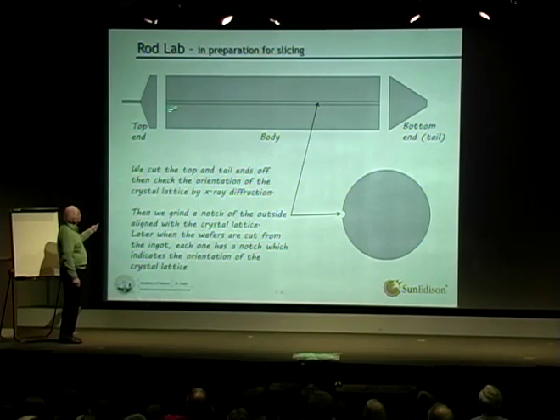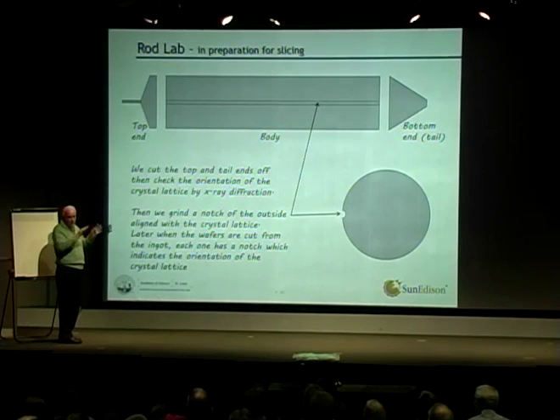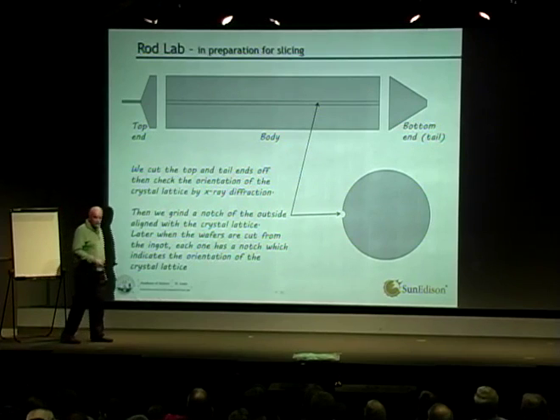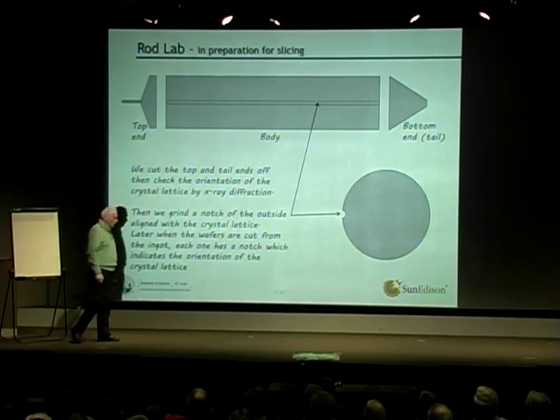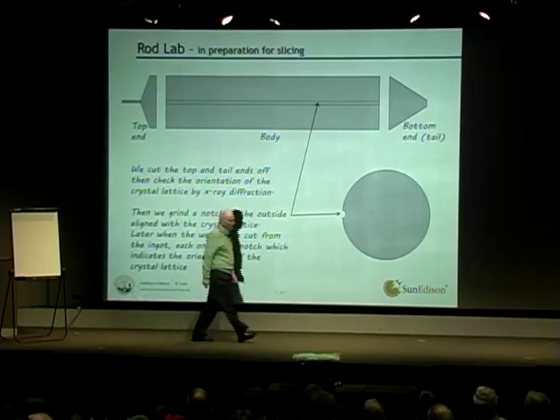Okay, so we take this body now, and this is the usable crystal. What we do is we grind the outside to remove all those little wobbles that we had because we were changing the pull speed in growth. So we grind the outside, we grind the notch, we cut the top and bottom off, and now we've got a nicely ground cylinder with this notch all the way down. And now we have to convert that to slices, to individual wafers.